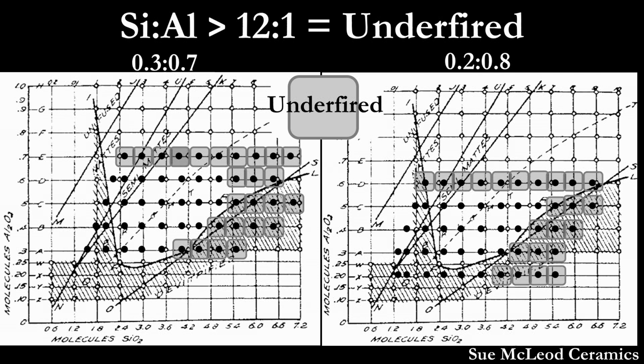On both maps, when the silica to alumina ratio was above 12:1, the glazes were underfired. This behavior was also predicted by Stull, where he calls them devitrified. I also found there to be a max alumina level, above which the glazes were underfired. That level changed according to the flux ratio. On map number 1, 0.3 to 0.7, the glazes dried up at 0.7 alumina. On map number 2, the glazes dried up at a lower alumina level of 0.6. This is because at 0.2 to 0.8 flux ratio, the glazes have less R2O, which is the more powerful of the two fluxes. Notice how the pattern of underfired is almost identical on both maps. The shape is the same, it just shifts on the map according to the conditions of what you're testing. If I were to increase the firing temperature, the whole pattern would just move upwards.